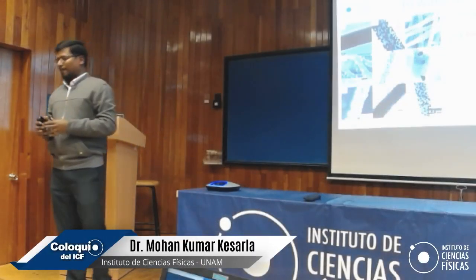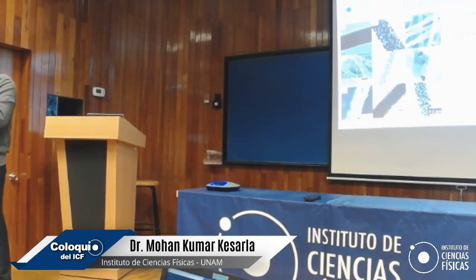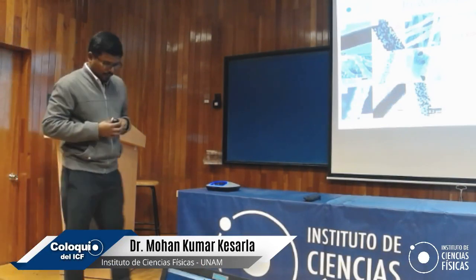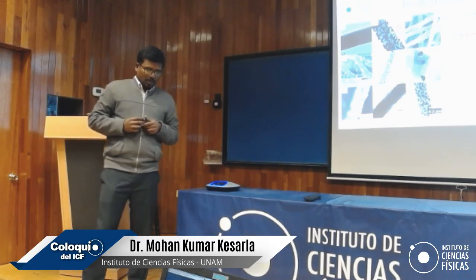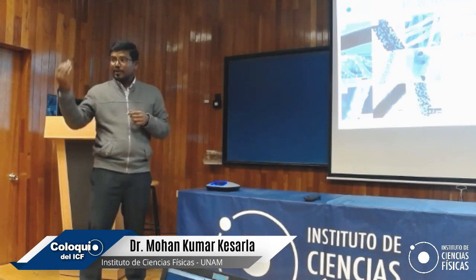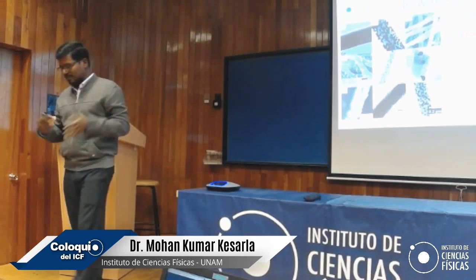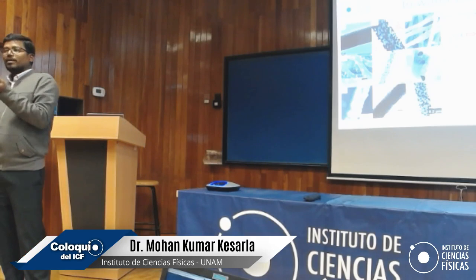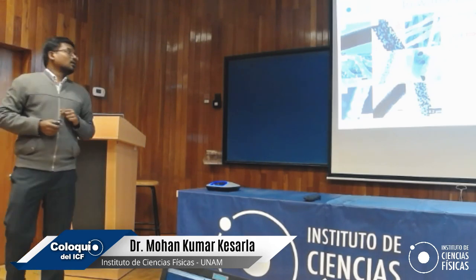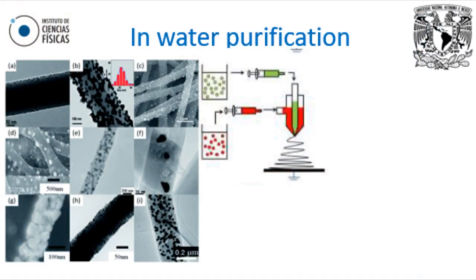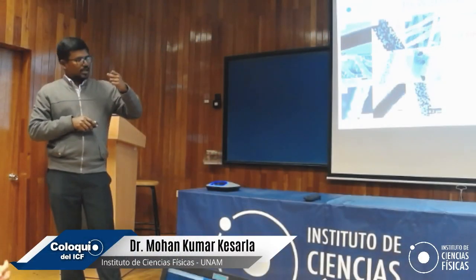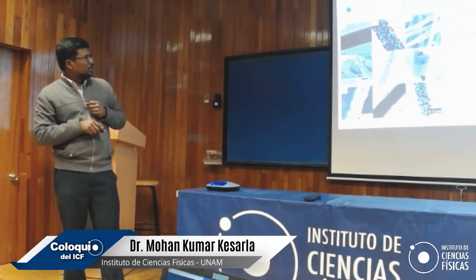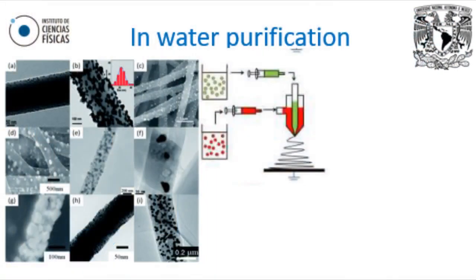But what we are doing in our laboratory, we got a project from a college for water purification. Here we are trying to incorporate the zero valent metals, which I talked about some time before on a slide, into the nanofibers. The problem is achieving good control on the nanofibers that we are expecting. It is very difficult. Sometimes the nanoparticles are seen on top of the polymer, sometimes inside the polymers, and sometimes we can get a fine dispersion. This needs once again good process control.